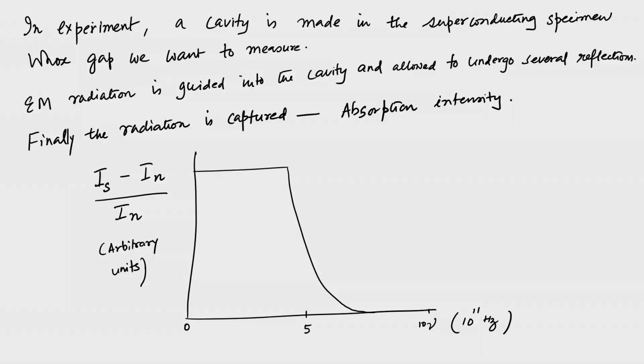Okay. So, what happens is that below a certain frequency, which is below 5 into 10 to the power 11 hertz, one actually gets the superconducting state having a larger absorption, and suddenly this goes to 0 in the vicinity. So, there is an absorption edge, and in the vicinity of that 5 into 10 to the power 11 hertz, it goes to 0, probably a little more sharp, but this is what we show here. I mean, this could be a little sharp depending on the material.